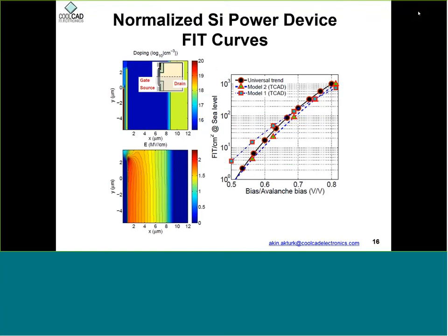What we did was we found a field-dependent failure rate, but in a distributed form. Once you get the field profile of a device, you can run this post-process and calculate failure as a function of position. Then you integrate it out to find the total failure as a function of area. So there are two levels of calculating the failure rate. One is to just use a formula that's based on the field and run a post-process to get the failure rate. Or you can do a detailed one.